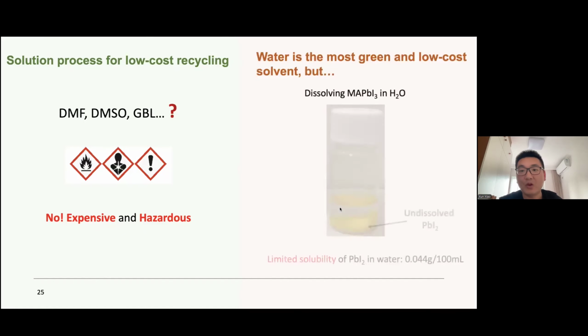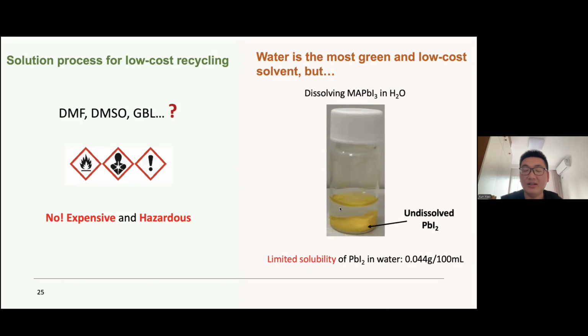So we want to use water, because water is the greenest solvent and also maybe the cheapest solvent. But when we tried to dissolve the perovskite into water, we found the solubility of lead iodide in water is actually not good. It has only 0.044 gram per 100 milliliter. So if we dissolve a perovskite like MAPI, a typical perovskite composition, the methylammonium iodide can be easily dissolved, but the lead iodide has a very different solubility. So if we want to do the recycling, the first thing that we need to solve is how to dissolve the perovskite completely with water.